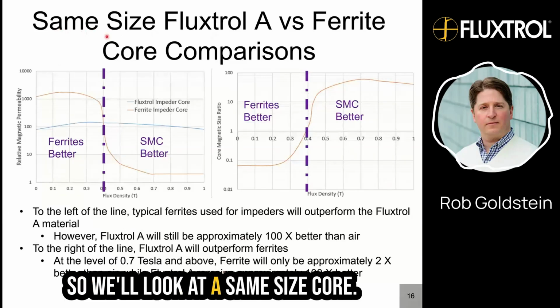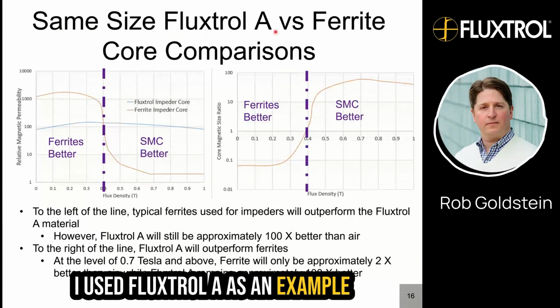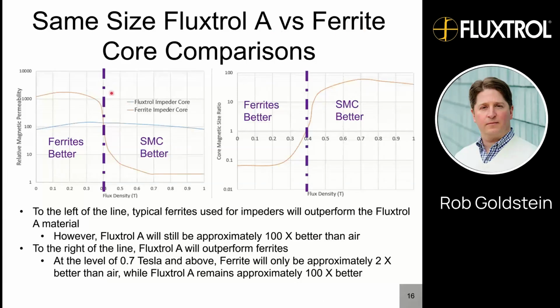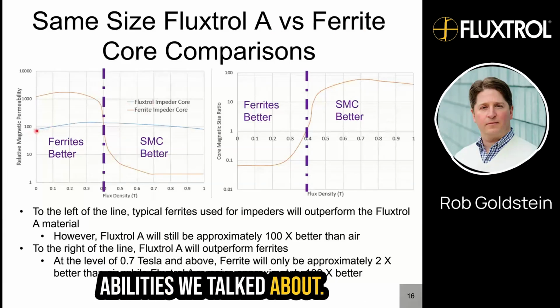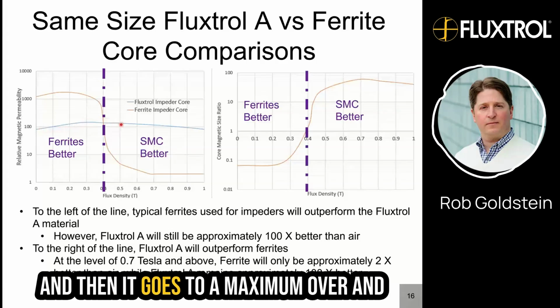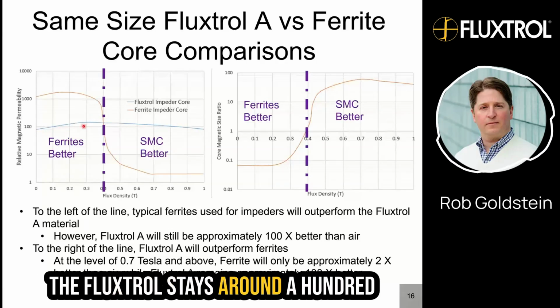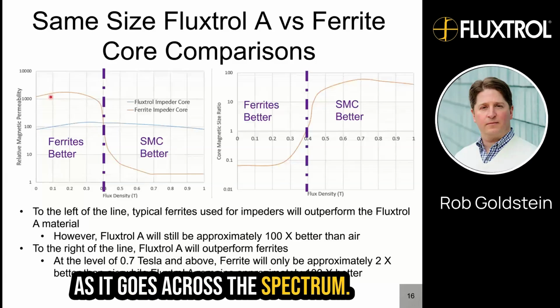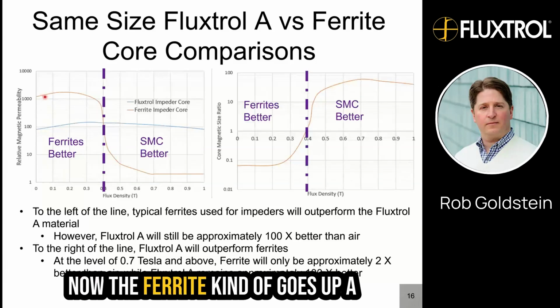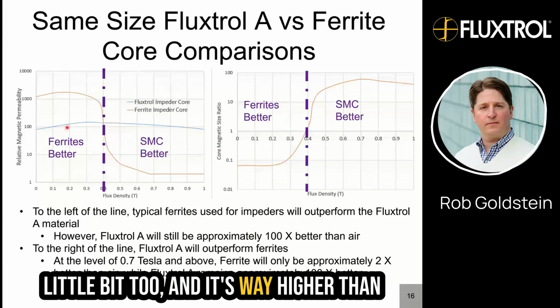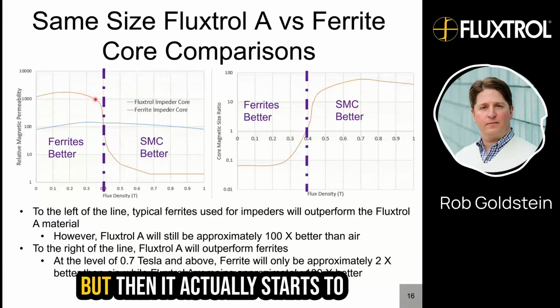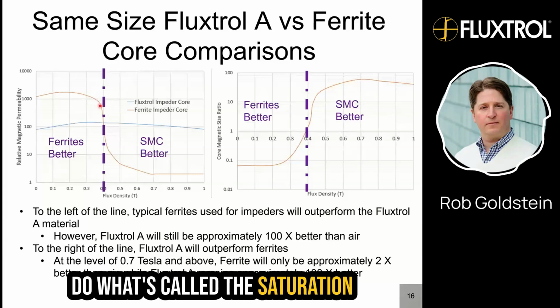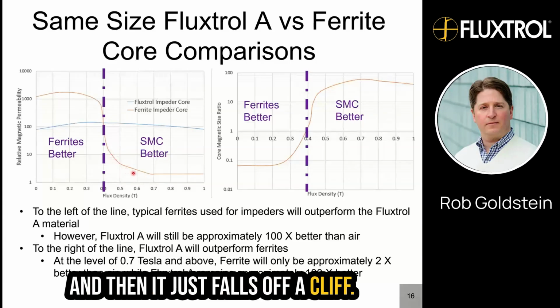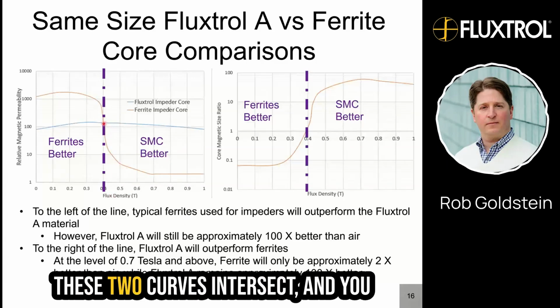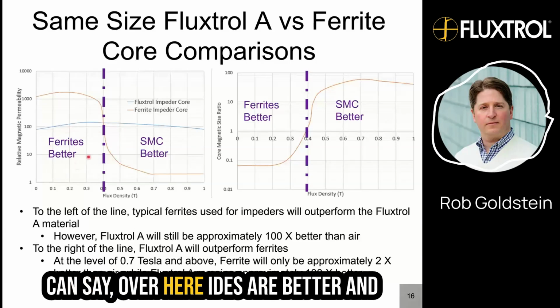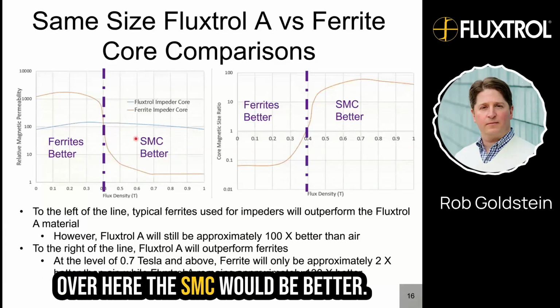So we'll look at a same size core. I used Fluxtrol A as an example material here versus a ferrite core. If you look, here are those permeabilities we talked about. You have your initial permeability, and then it goes to a maximum and over. The Fluxtrol stays around 100 as it goes across the spectrum. The ferrite goes up a little bit too, and it's way higher than the Fluxtrol by an order of magnitude. But then it starts to saturate, and it just falls off a cliff. We can draw a line where these two curves intersect, and you can say over here ferrites are better, and over here the SMC would be better.